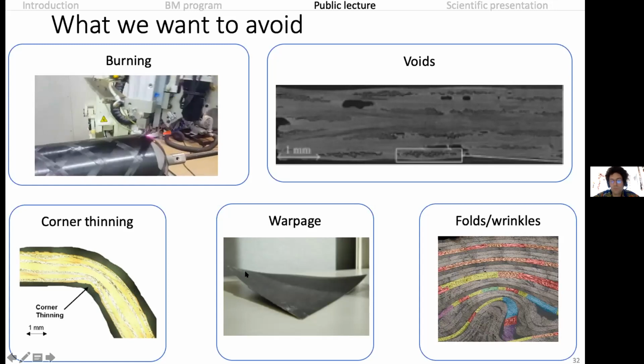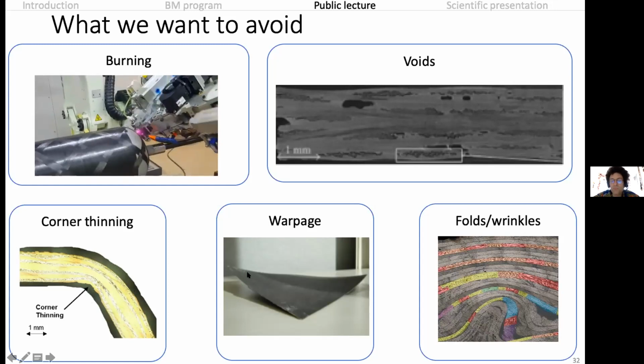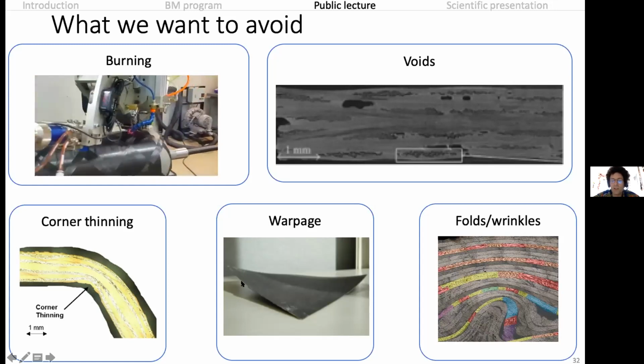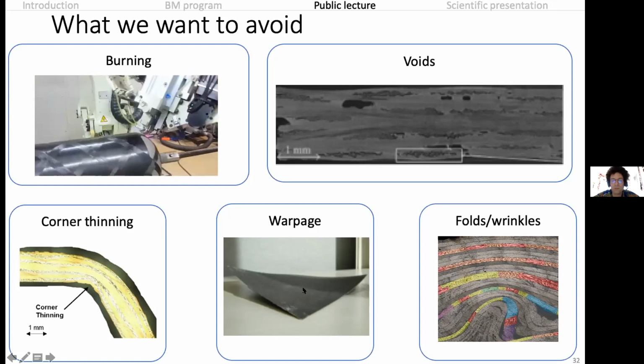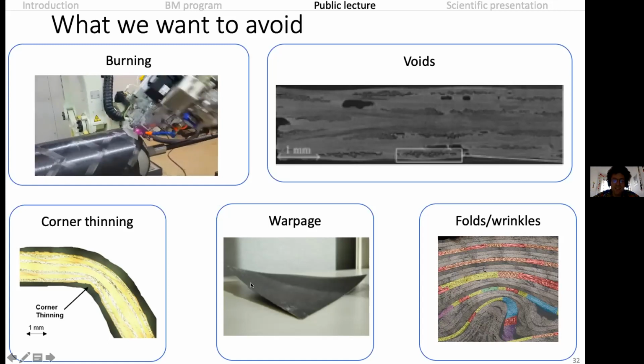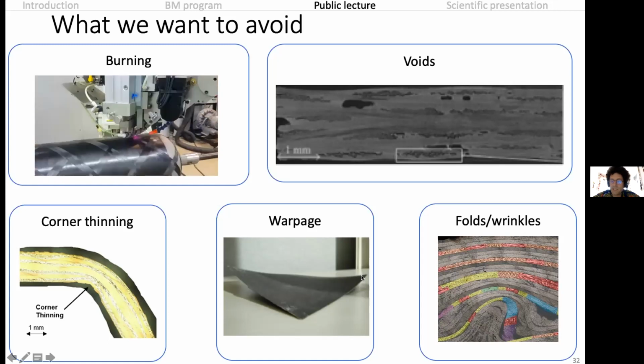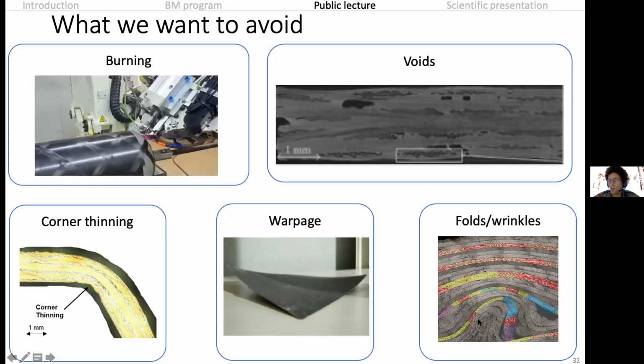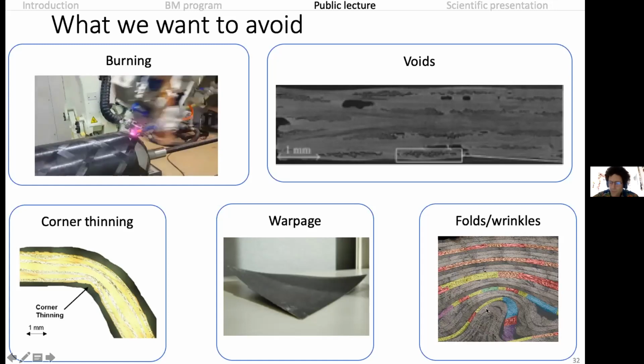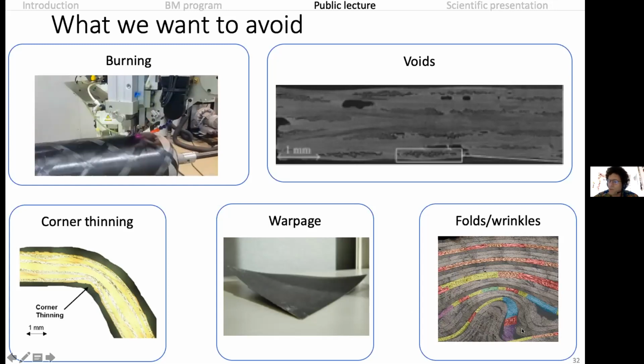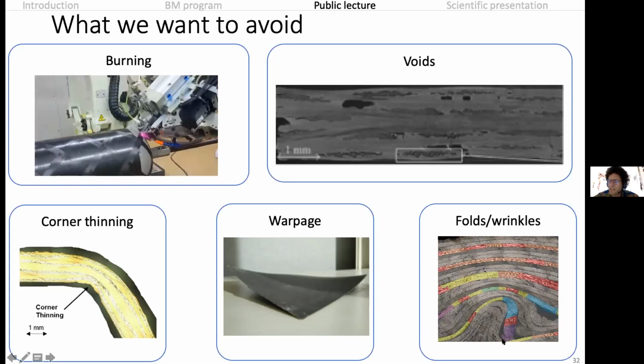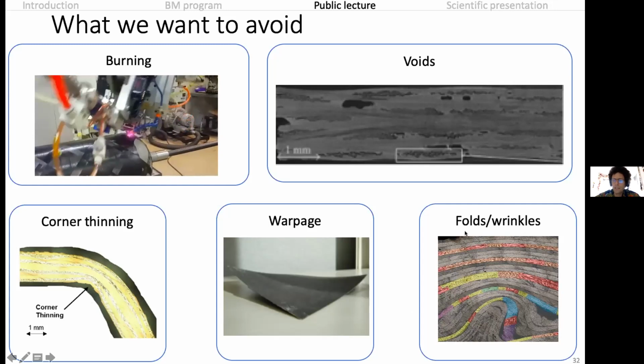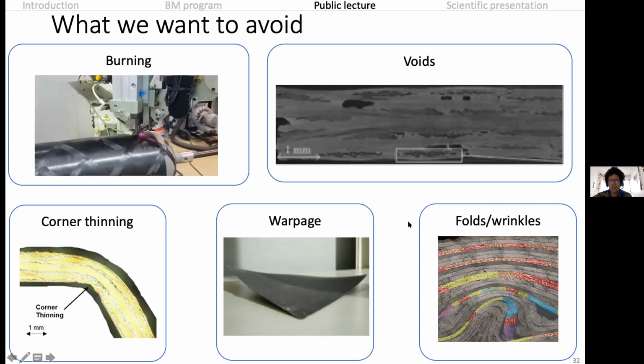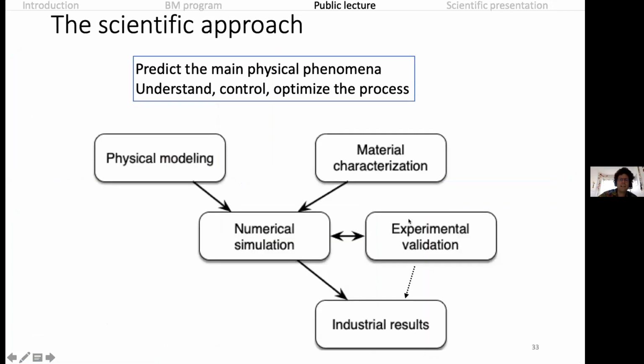You have some residual stresses. So you're trying to manufacture a flat plate, and luckily it comes out not flat at all. It's really a banana shaped plate. So this might be a defect. You might have also all these textile layers that may slide and make some wrinkles and have some defects inside your stack of layers. So we try to avoid that.